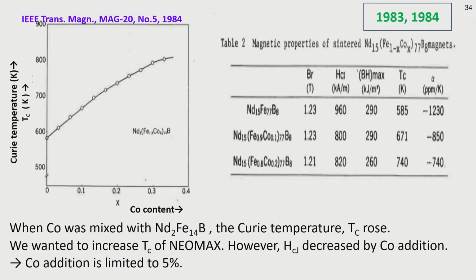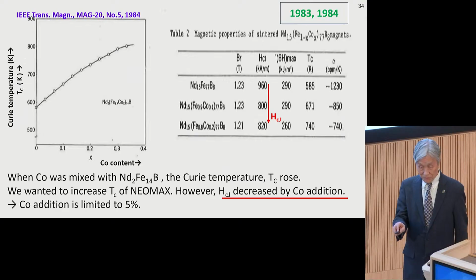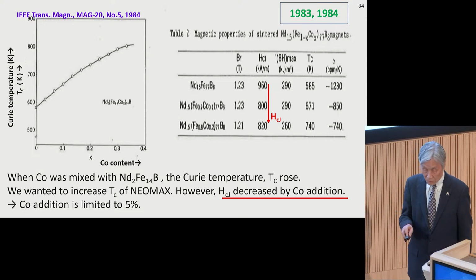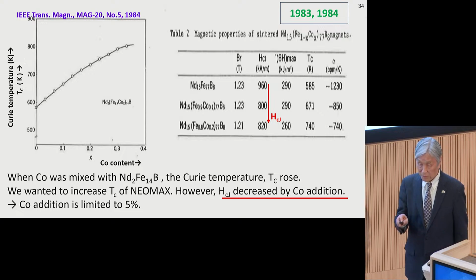And when cobalt was mixed with neodymium 2 iron 14 boron, the Curie temperature increases very rapidly as the cobalt content increases. However, the coercivity decreased by the cobalt addition. HCJ decreased by increasing the cobalt content in the sintered magnet. So we cannot add too much cobalt. So cobalt addition is limited to 5%.